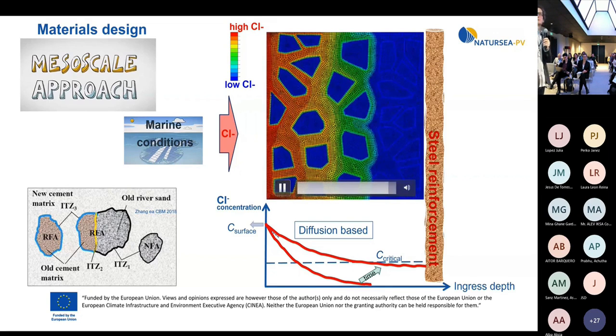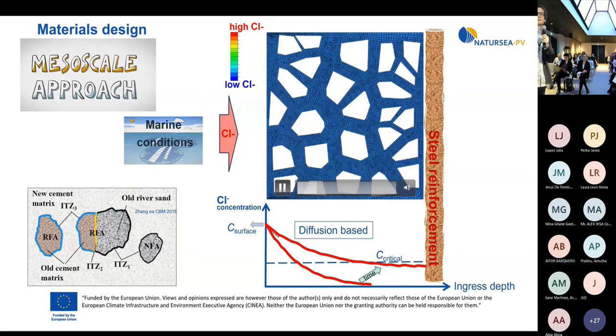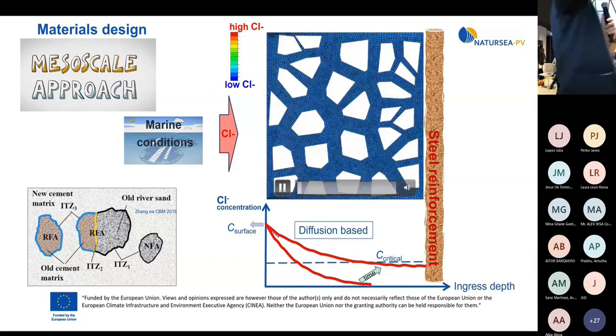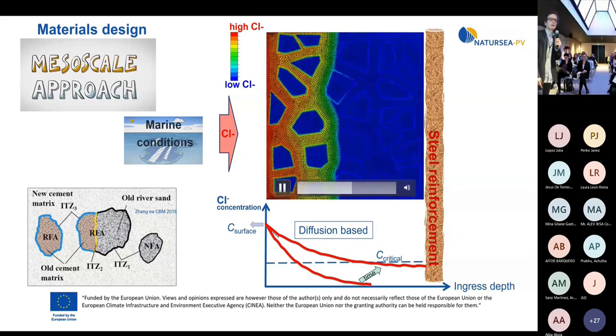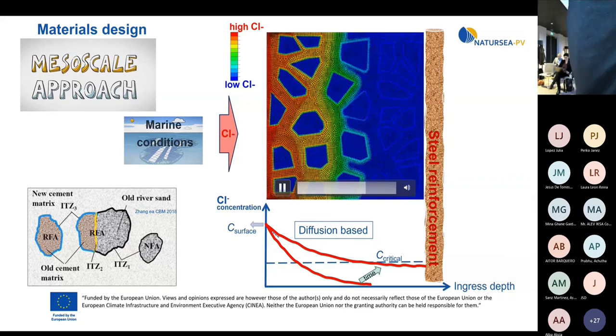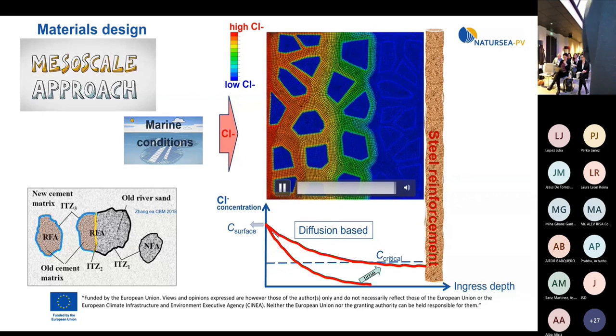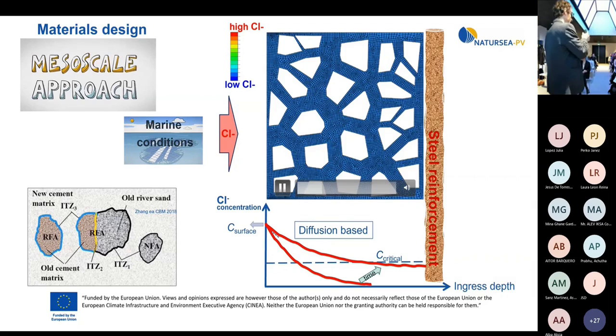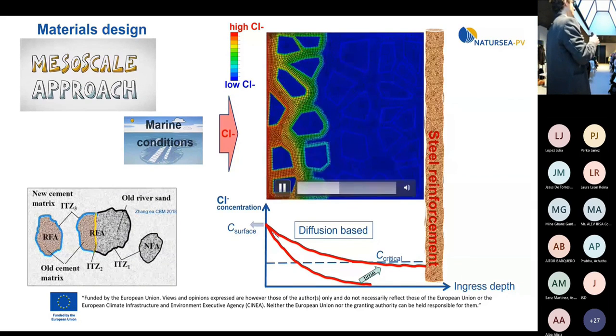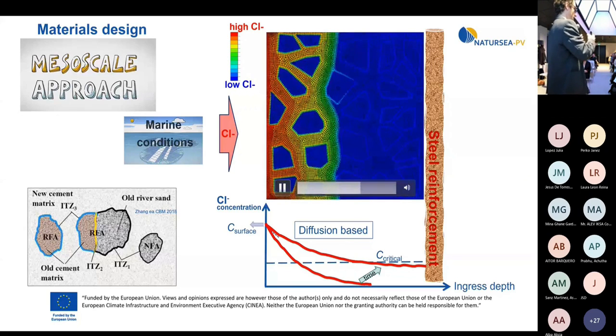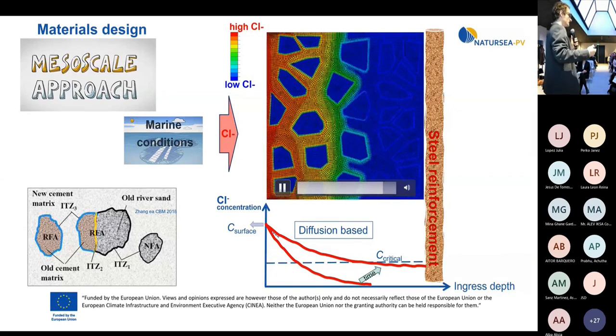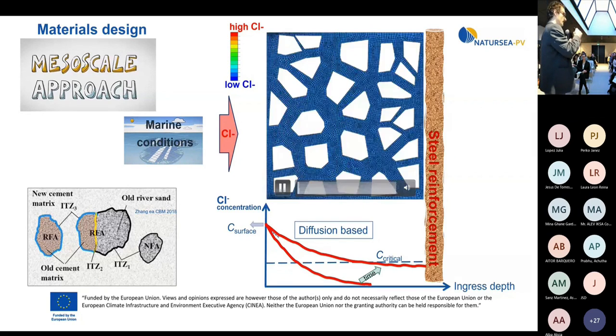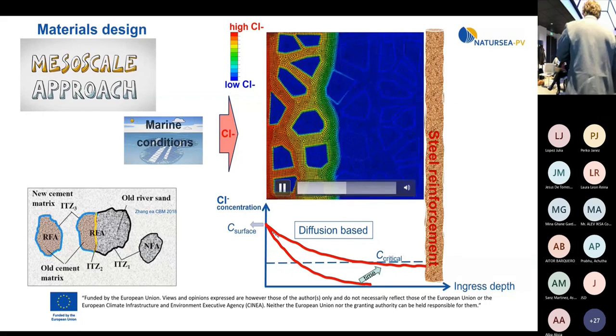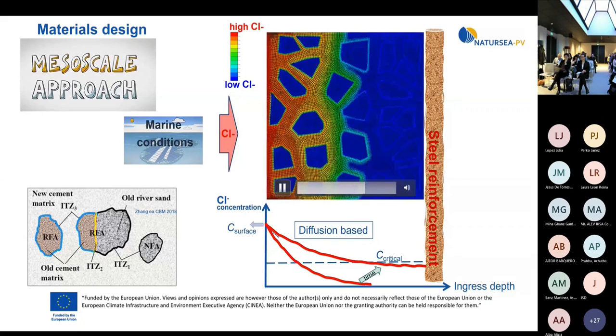But now we have new materials, so we have blended cementitious materials. I'll talk about that later, but first I will talk about the aggregates. We want to use recycled aggregates, and here this is a natural fine aggregate. If you use recycled aggregates, they also contain attached mortar, or attached paste, because they were already in the matrix of the paste. When you crush them, you have not only the aggregate but also the mortar or the paste. So we have different types of interfacial zones that will then influence the chloride ingress.